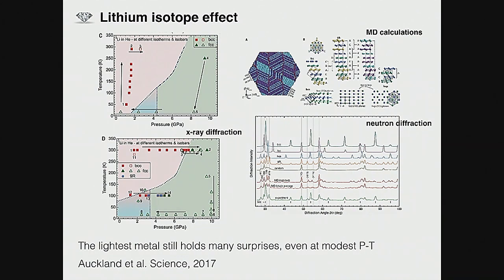Hence, you have a change in the kind of crystal structures you get for these light element, different isotopes structures. And another very intriguing aspect of this work is that by using different PT paths that include pressure, of course, they claim that the ambient pressure, low temperature phase, so the ground state of lithium, is actually different from the one that has been accepted for the longest time.